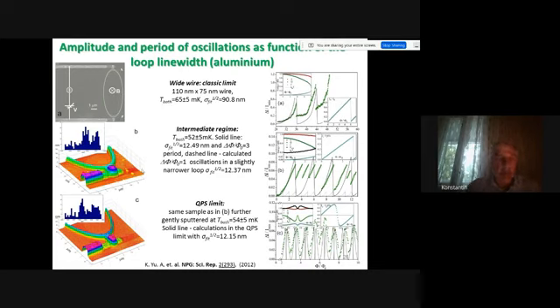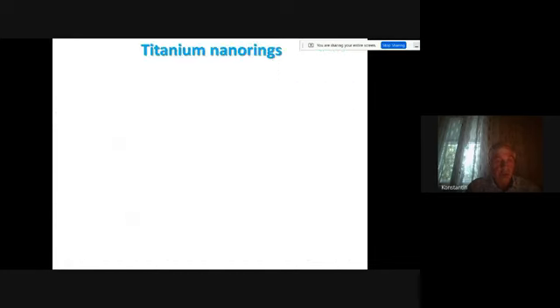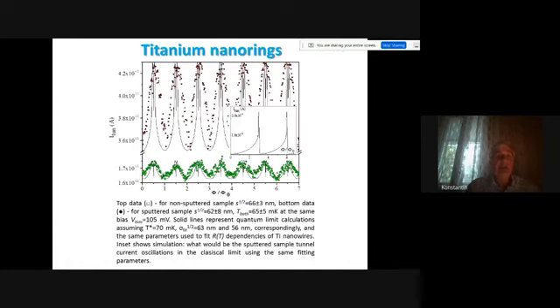And here are our structures. First structure, which has sufficiently thick walls, no fluctuations. And then after several cycles of ion milling, it becomes much narrower. So when the walls were thick, we have a huge amplitude of oscillations of current with large periodicity. Then the period starts to be stochastic. And then finally, when we go to quantum limit, the periodicity starts to be strictly one flux period, and the shape is not anymore sawtooth, but it starts to be degenerated sinusoidal type. And the same effect has been observed in titanium, even on larger scales.